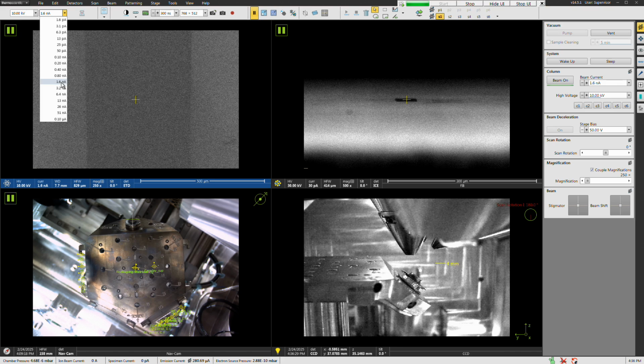Again, to some degree, your resolution is going to be limited by probe size. So going lower here is going to help you in that regard, okay? But I know with this sample, even though the grains are smaller, they're still fairly micro scale. So you probably don't need to go this low. So I guess we can put this at 6.4, just to make things a little easier for us, and that should still allow us to resolve everything we need to resolve. All right, so I'm not going to hit wake up because we don't need the FIB beam. I'm just going to hit beam on here.